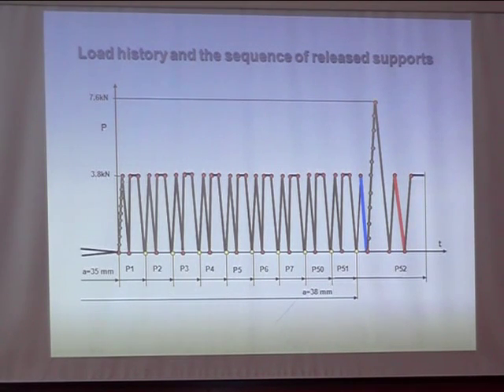So I started from 35 millimeters, and then we applied a cycle, as you see, 10 increments per one reversal. But actually there were more iterations, because if that increment went over from one element of the stress strain curve to another, we had to back up everything and find such a smaller increment that you ended at the end of linear elements, and then we went further on. So there was a lot of iterations between. This is how we were inputting, but the computer was dividing the stress strain curve into even smaller elements just to follow exactly what was given, because otherwise we would accumulate a lot of error.